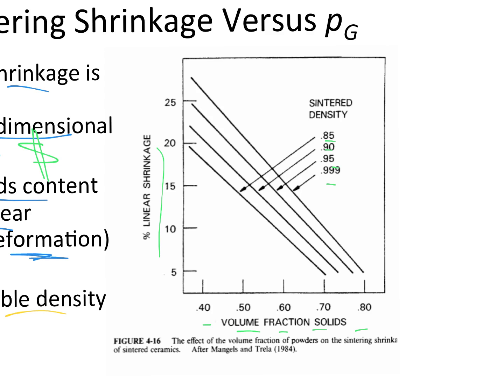From the biomaterials perspective, we would love to be at 0.9999, if not better than that. 0.999 means the flaw sizes are as small, at least we think, as we can possibly make them. So we'd really like to get to that outer curve. At the same time, though, we don't want this to shrink too much, because shrinkage means it's changing shape. So if we start with, say, 40 volume percent, which is pretty pitiful in the scheme of things in terms of injection molding density, in order to get to this final